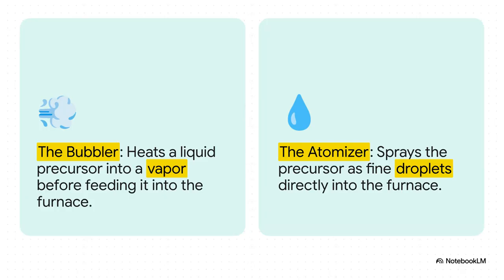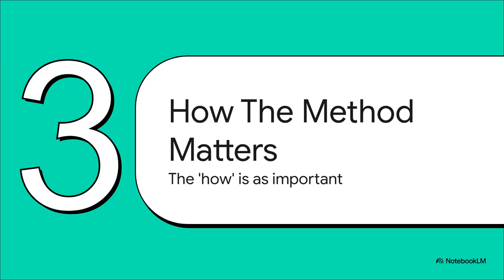The researchers tried two different ways of getting the ingredients into the oven, so to speak. The first one, the bubbler, is kind of gentle. It heats up a liquid until it becomes a gas, and then that gas flows into the furnace. The second one, the atomizer, is much more direct. It's basically like a fancy spray can that shoots a fine mist of the materials straight into the heat. And this is where things get really, really interesting. Because the scientists discovered that the method they used, the way they made the particles, had a massive impact on the final product. It turns out the how was every bit as critical as the what.